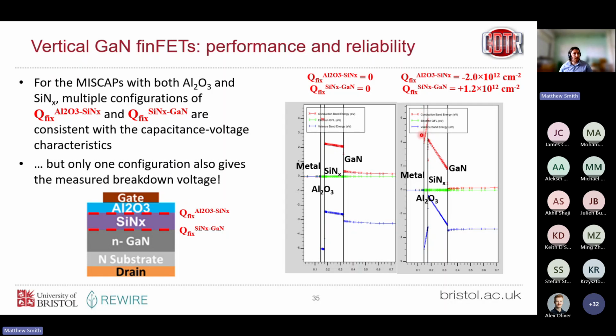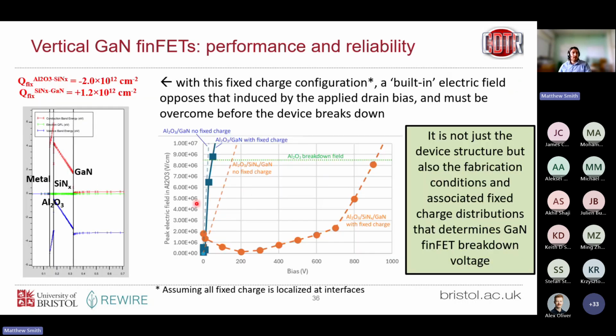As we add the fixed charge at the interfaces, negative charge here brings these bands up, positive charge brings these bands down. So we get this electric field. And that electric field is built into the device because of that fixed charge. So when we apply a bias on our device, the electric field resulting from the applied bias has to fight against this built-in electric field in the device.